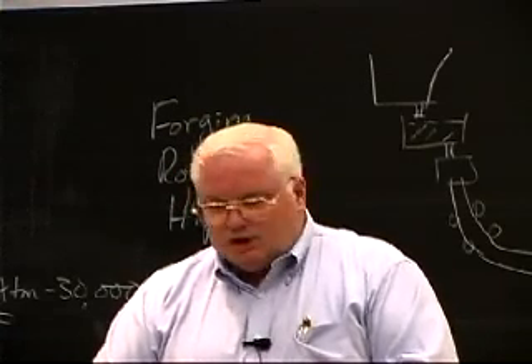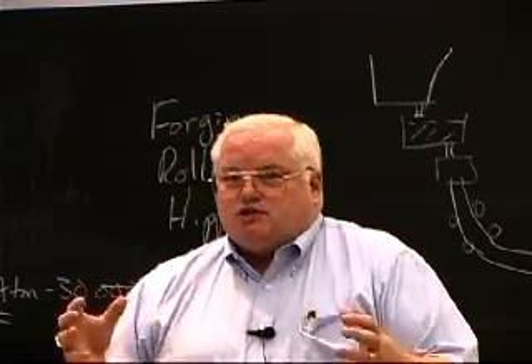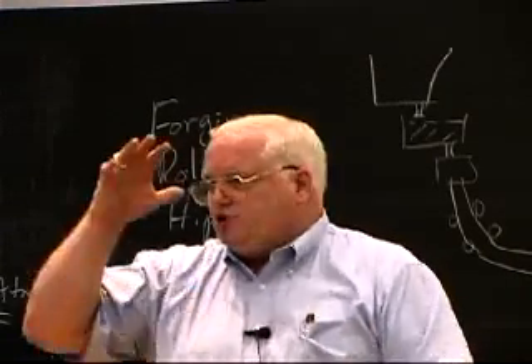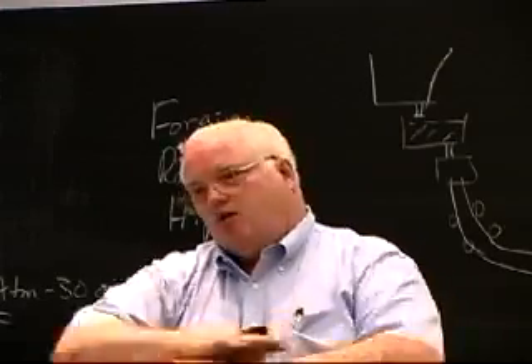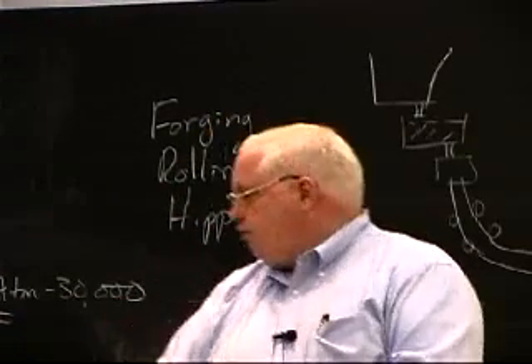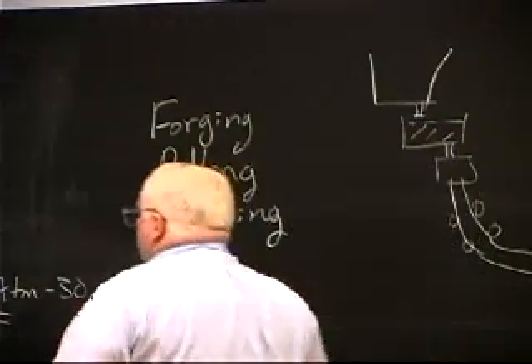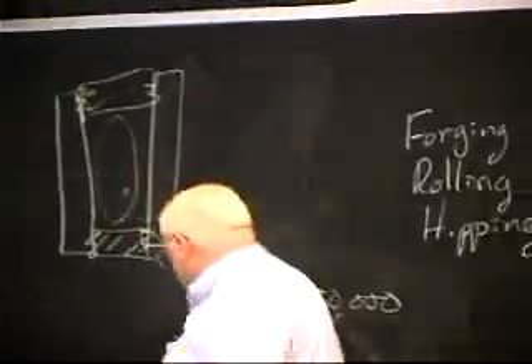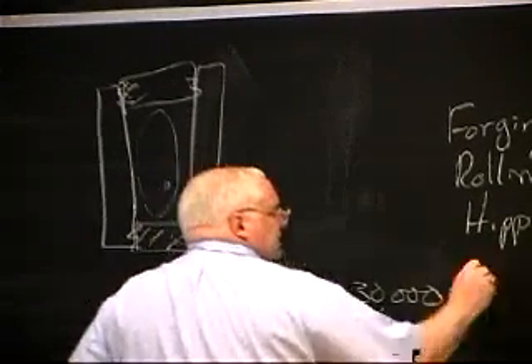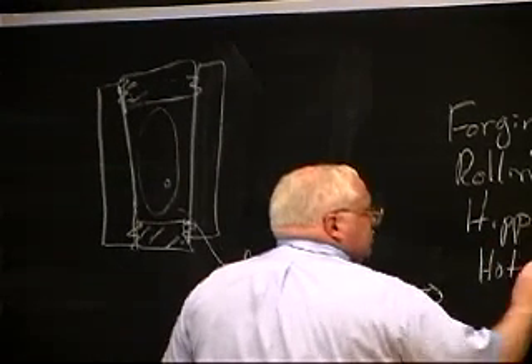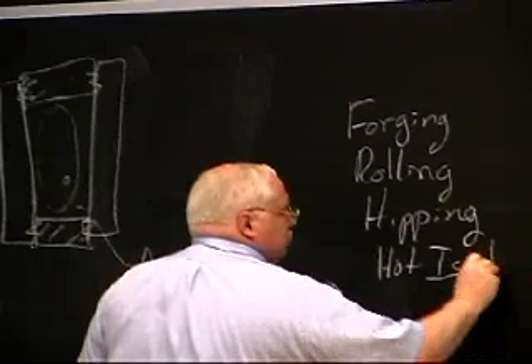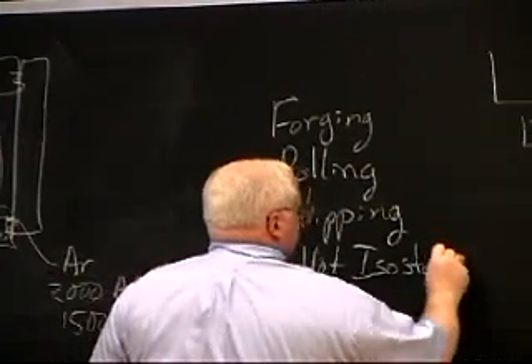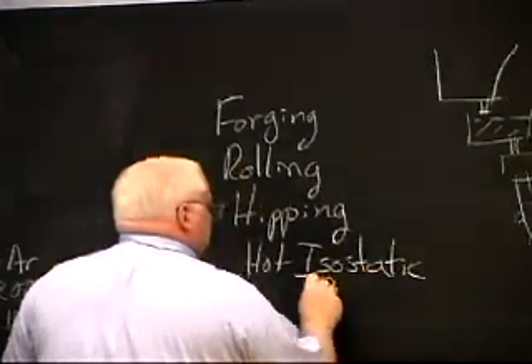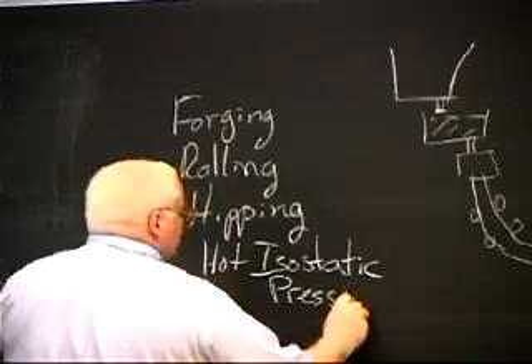Well, it turns out the advantage of this is you don't have a lot of shape change. In forging, you have a lot of shape change. In rolling, you have even more shape change as you're deforming the material. Here, you're not deforming the material, you're just squeezing it. Hipping stands for hot isostatic pressing. So you're doing it at temperature.